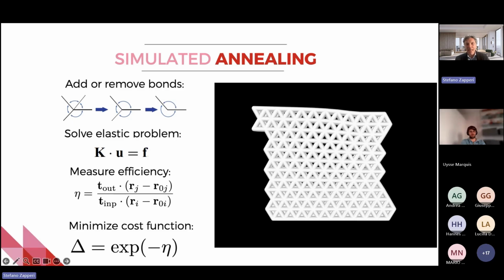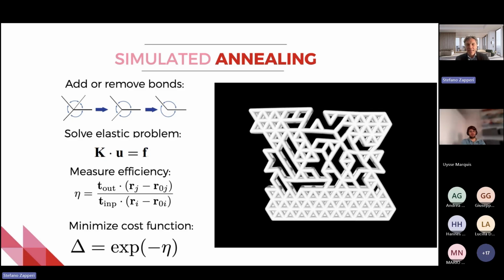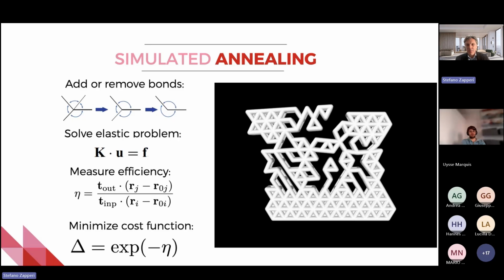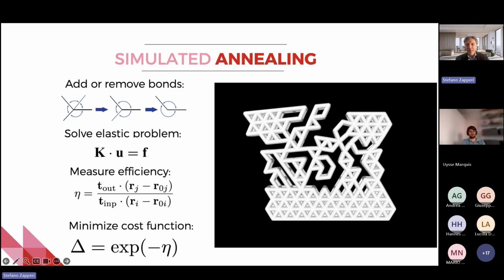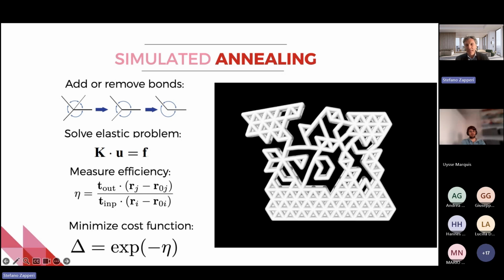And then we create a cost function, in this case, the exponential of that, which we try to minimize. And we do that as if this was an energy, and we do a sort of Monte Carlo, in this case simulated annealing, until we find some structure that we like. So you see this structure here is moving to the left as it's been programmed to do. So in this case, we don't design the structure ourselves, just thinking what's the best strategy, but we let the computer do it in typical statistical physics way.